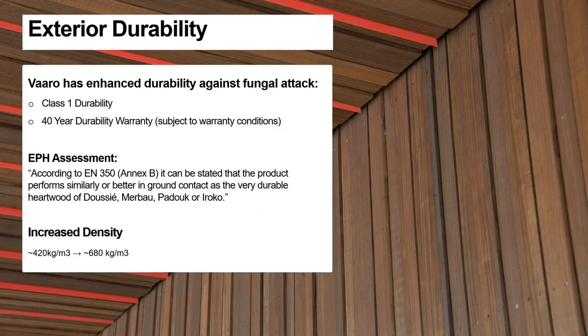So we conducted testing to European standards for in-ground testing, and the product performs to a Class 1 durability standard, otherwise known as Use Class 4, similar to old-growth tropical species of high durability. And this has really allowed us to offer an extended 40-year durability warranty for the timber. Similarly, the properties of the wood have changed, so the density is increased from 420 kgs a cube up to around 680 kgs per cube. This makes it more resilient and gives it a higher level of hardness.